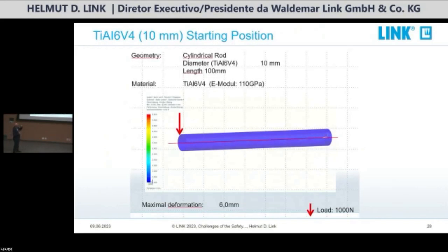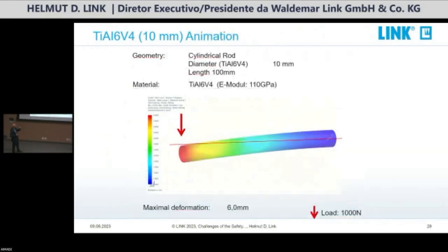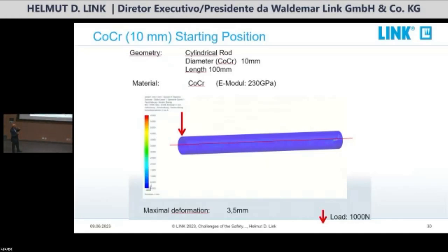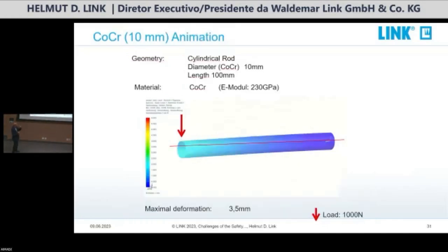you see a cylindrical rod of 10 millimeters. Titanium, E module, 110 gigapascal. We load it with 1000 Newton, and the maximal deformation is 6 millimeters, like you see here. 6 millimeter deformation with a load of 1000 Newton, E module 110. Now, when we do the same thing with the same rod, 10 millimeter, with cobalt chromium, you see that the deformation is only half of it, 3.5 millimeters. Same load, same size, but 3.5 millimeter.